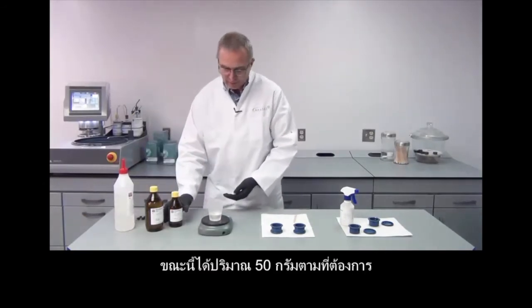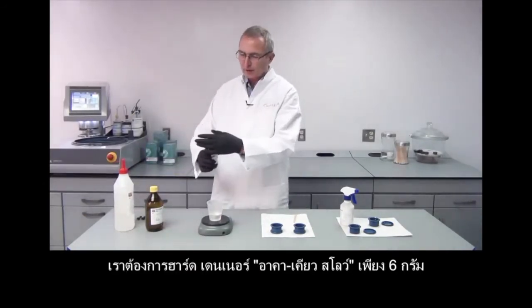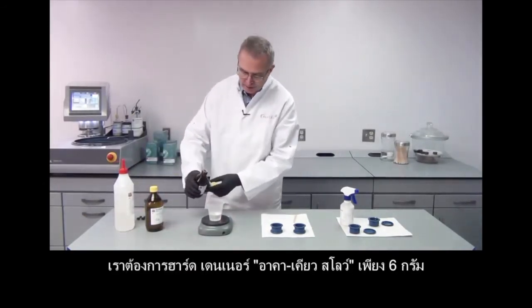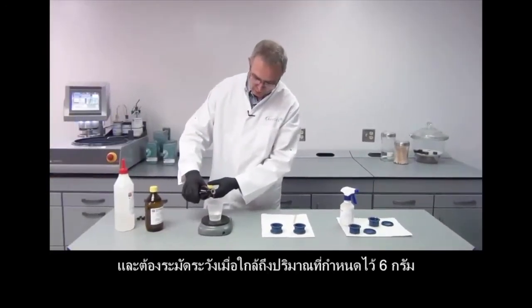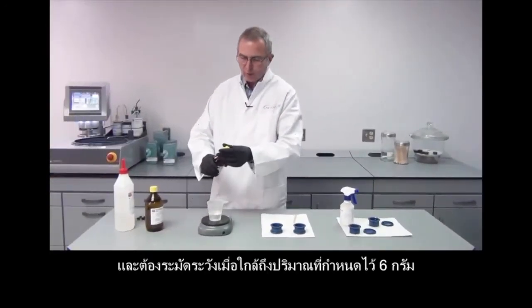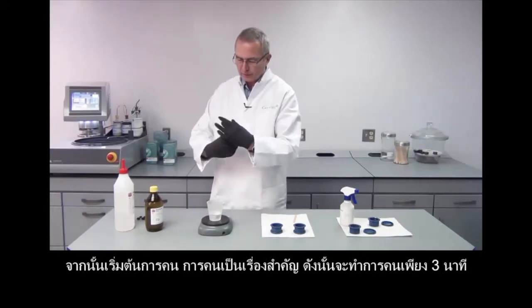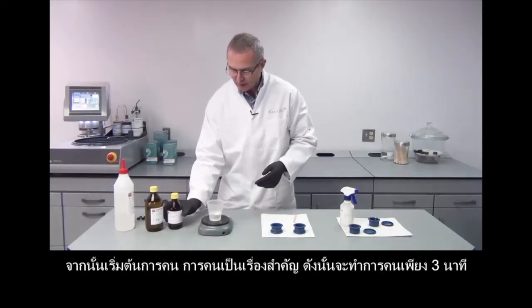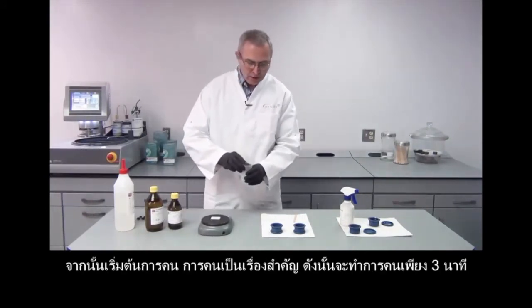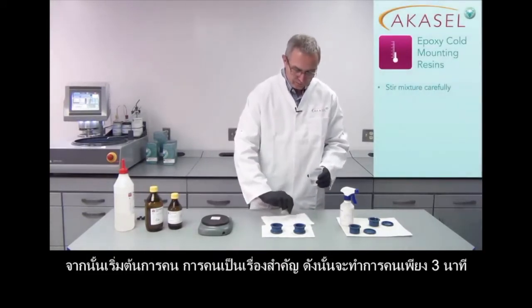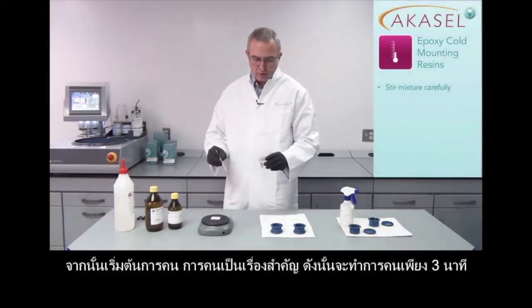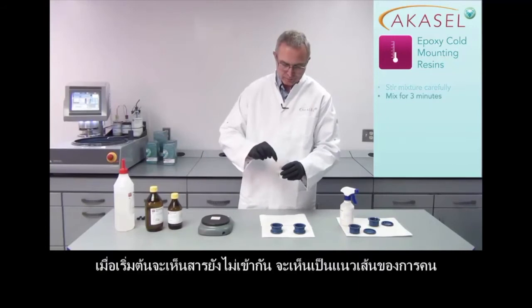I have now exactly 50 grams, and then I use my hardener, and I have to fill in 6 grams of the hardener. Again, I'm very careful towards the end. Put in my 6 grams of hardener, and now I can start stirring. Stirring is very, very important, and I have to be thorough. I have to stir for about 3 minutes.